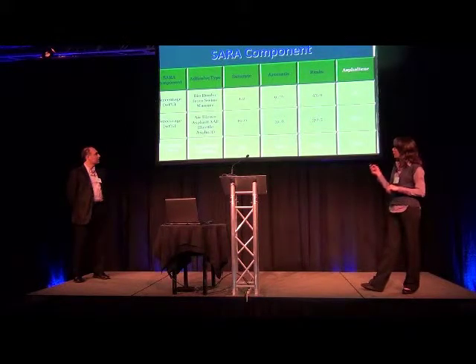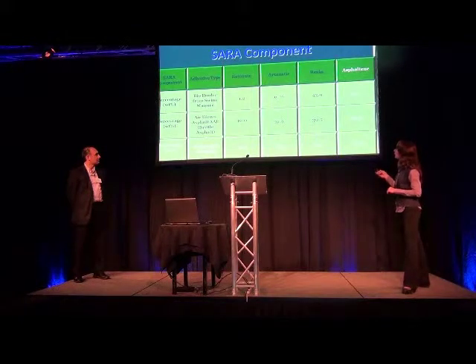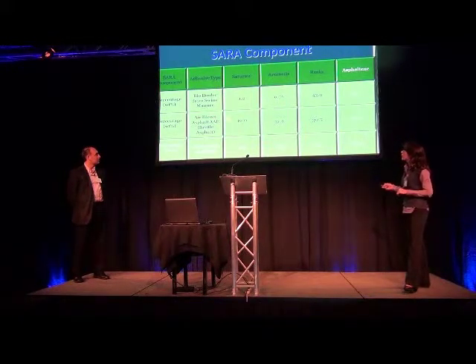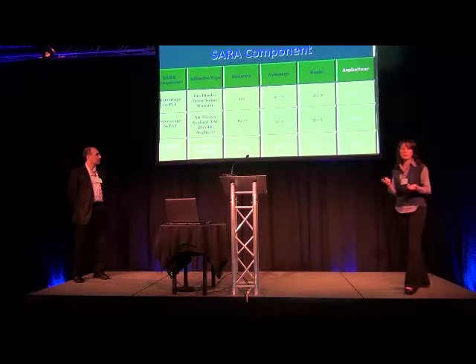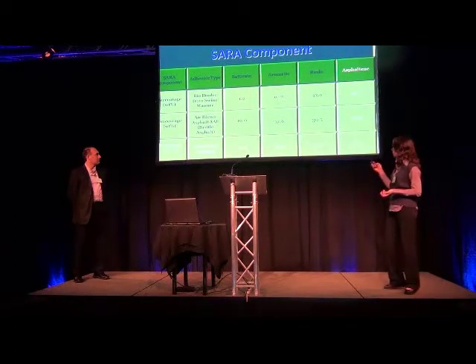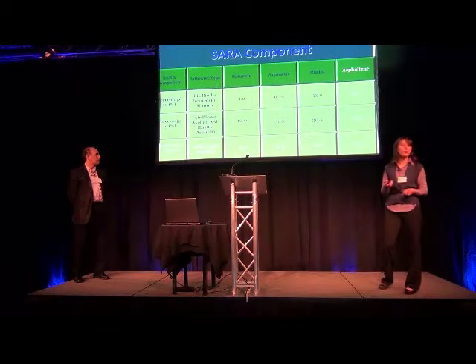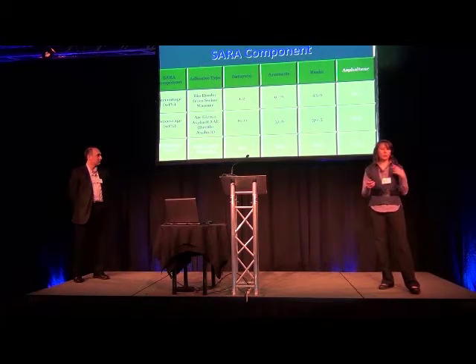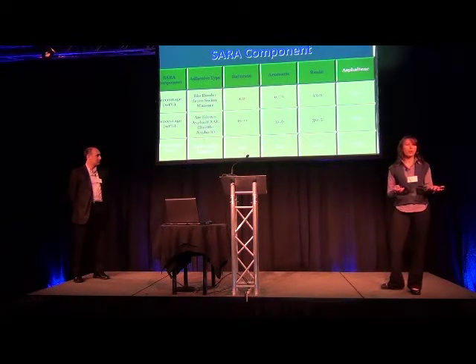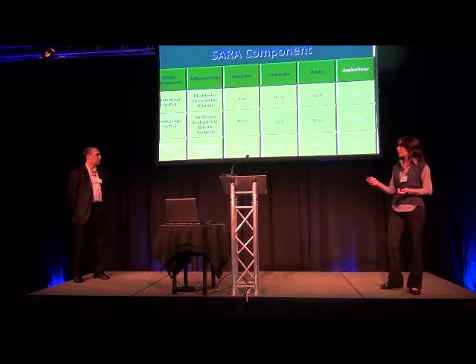So we also looked at the saturates, aromatics, resins, and asphaltenes components of several asphalts and the adhesive. So these are typical asphalts used in the colder states here, and hot states like Texas here. And this is our adhesive, basically. So we have certain features that are similar to the asphalt. Of course, the percentages are different. You have different percentages of saturates, aromatics, resins, and asphaltenes. But at the end of the day, it matters how it performs and how it passes all those specification criteria.